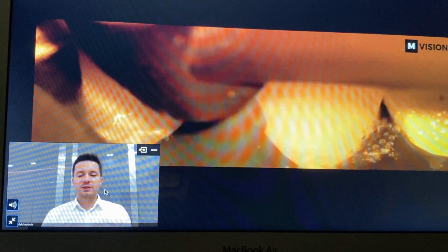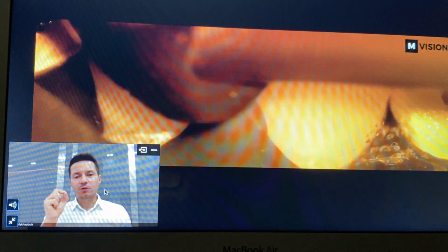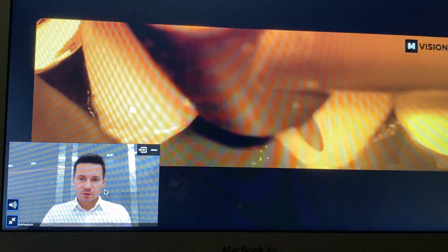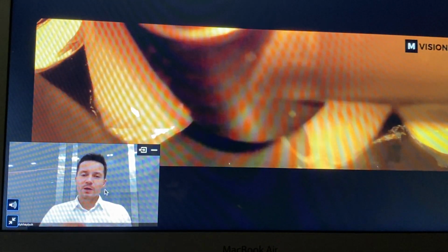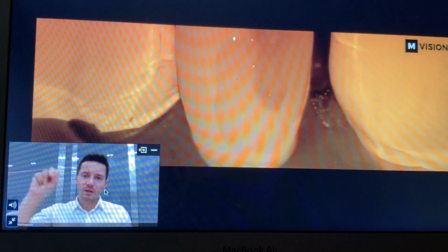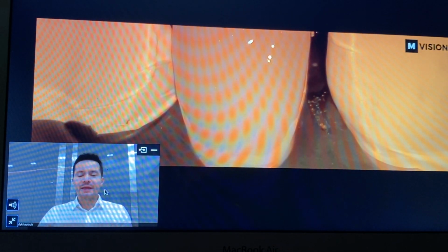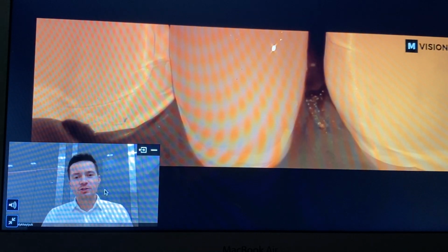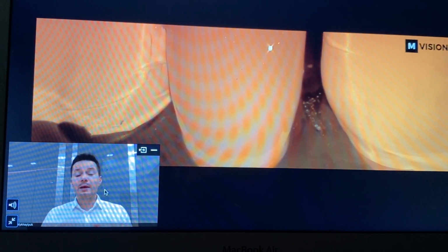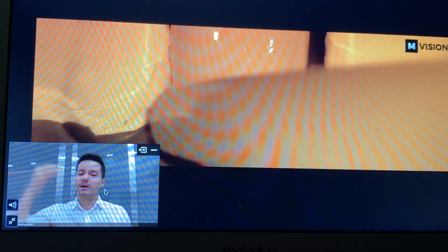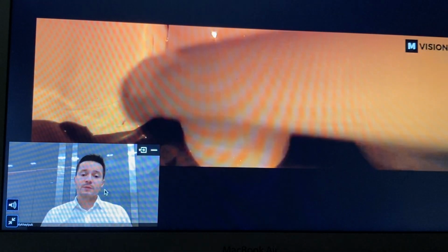Why? Because ceramics cannot be created as a feather edge, just like a metal. If you don't polish the transition, with a probe you will always be able to feel where the tooth is and where the ceramic veneer starts. And that zone will be a retention zone for plaque and, as a result, inflammation of the soft tissue, staining, and other problems in the future.